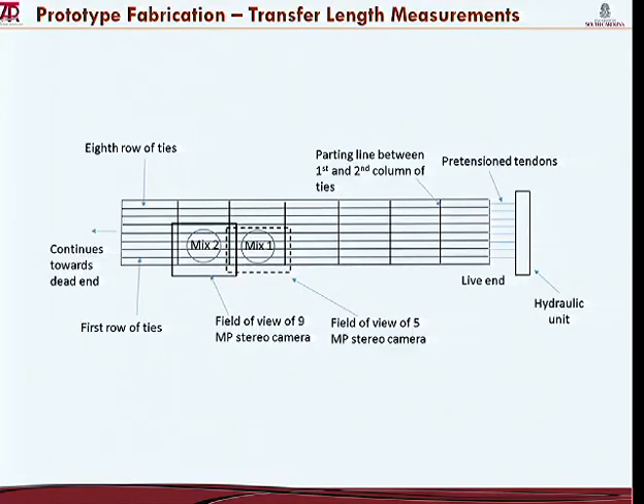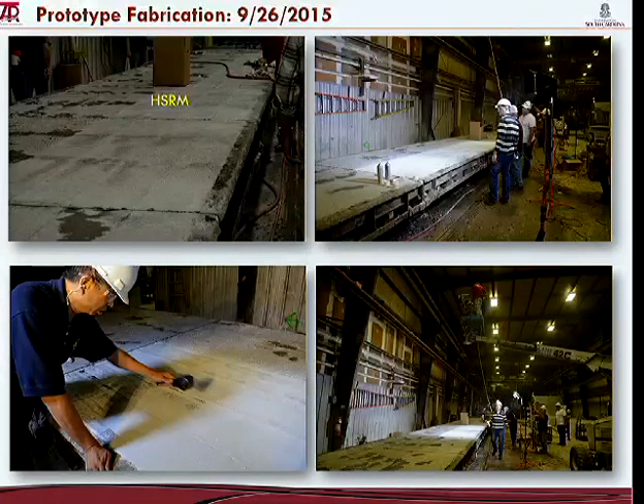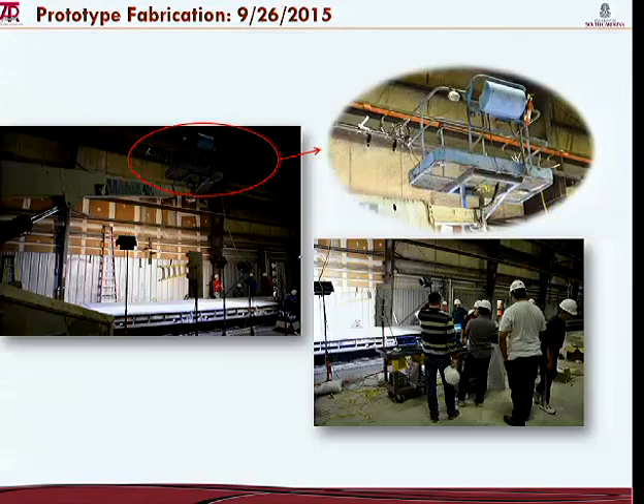This is the cavity or the bed, the pre-stressing bed, and mix one is the reduced modulus ties that we will be monitoring with DIC. So the surface is prepared. We see the lighting. We do apply the speckle here with a roller, and the system is attached to the lift here. This is a detail, about 17 feet above the surface of the ties, a well-lit surface, and images are taken before strand release and after strand release.